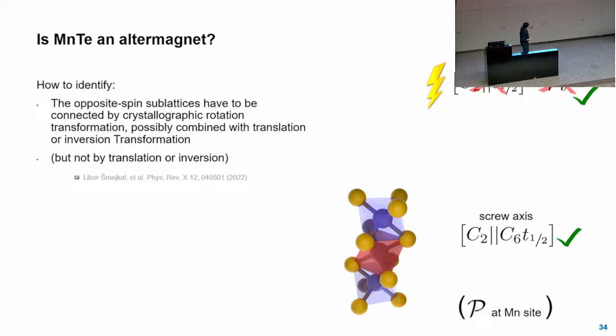However, now when we do a slightly different operation, such a twisting and pushing operation, called a screw axis, it's exactly what is written here. We have a crystallographic rotation transformation, in this case a 60-degree one, and at the same time we shift the atoms by half a unit cell up. And in addition, we change the color from blue to red. So now we have in fact shown that yes, the blue and the red lattice are connected by this rotation-like symmetry operation. So in fact, symmetry tells us this is an altermagnet. So now we just have to find a way to measure it.